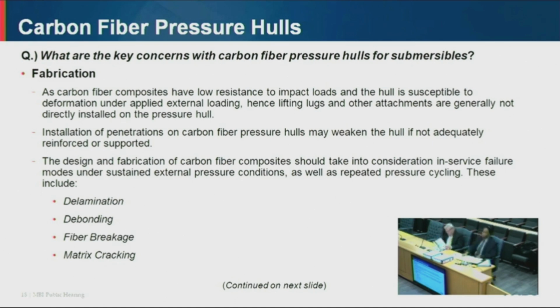Now, carbon fiber composites have a low modulus of elasticity, low shear strength, and they are brittle materials with low impact strength, okay? So they have very low resistance to impact loads, and the hull is susceptible to deformation under applied external loading. Typically, lifting lugs and other attachments are not directly installed on carbon fiber composite pressure hulls because they cannot withstand localized loading, and they tend to deform under it. If you install penetrations on the carbon fiber composite pressure hull, that means you have to make openings in the pressure hull. That will weaken the pressure hull because the main load-bearing members in a composite are the carbon fiber strands. So if you cut the strands to make an opening, you're going to weaken the pressure hull. So reinforcement of the openings is very critical. If you don't reinforce it, you can have stress risers in the vicinity of the opening, and that can lead to cracks and failure of the pressure hull.